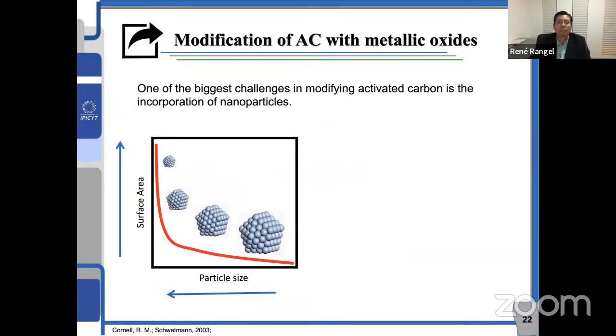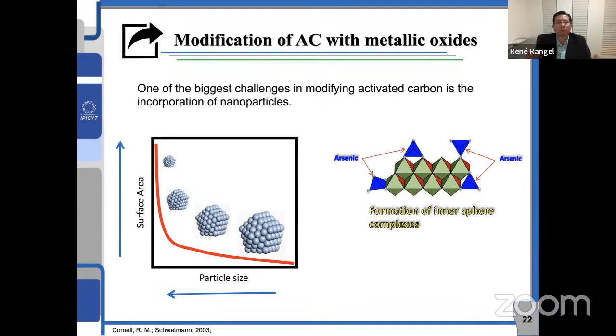Well, what have we done to face this problem? Some years ago we said, okay, let's synthesize some metal oxides and hydroxides, but as small as possible. We know that if we reduce the particle size, we increase the exposed surface area. If we have a bigger surface area, then we expect a higher adsorption capacity, for example, for arsenic. It has been published many times that iron oxide is very selective for arsenic 5. The mechanism has to do with inner sphere complexes, bidentate or monodentate. And again, if we reduce the particle size, the surface area will increase, as I showed in the graph. So hopefully we will have a very good adsorbent.